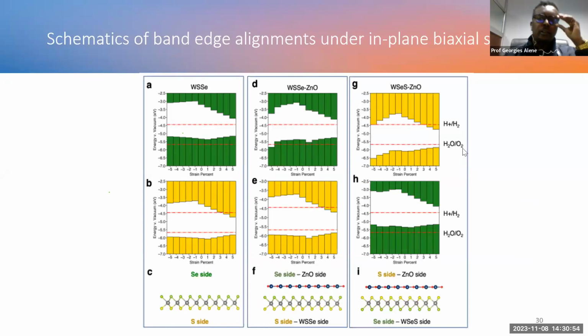Then we are interested in photocatalytic application. So we draw together the redox potential of the water. This is the dashed line, together with the band edge values of the materials. So we studied three cases. One is using only WSSe. The other two are the heterostructures we have selected before. So if you see here, for example, for WSSe, it has two sides.